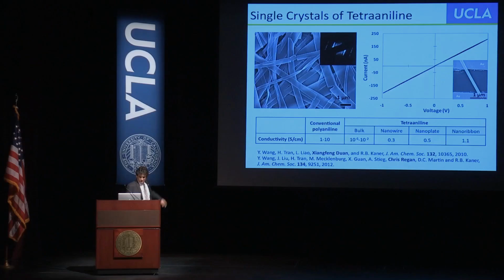And so this 4-unit long segment has a conductivity almost as good as the bulk material, which is 1 to 10. It's over 1. And so this is remarkable. And it means that the electrons in this material can hop very nicely from one place to the other if you align it perfectly. In fact, this material is so well aligned. We did this with Chris Regan in physics. We were able to get single crystals of this. And I just want to show you one single crystal.